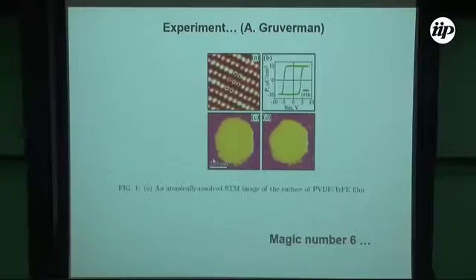It's not perovskite anymore. It's some kind of PVDF-TrFE, I don't know what material, which is a uniaxial ferroelectric, and even more, the background lattice has no high symmetry axis. It's an absolutely low symmetry ferroelectric with up-down directed polarization. What they observed is that the domain created after the start moment becomes hexagonal. There is no background hexagonal symmetry here.